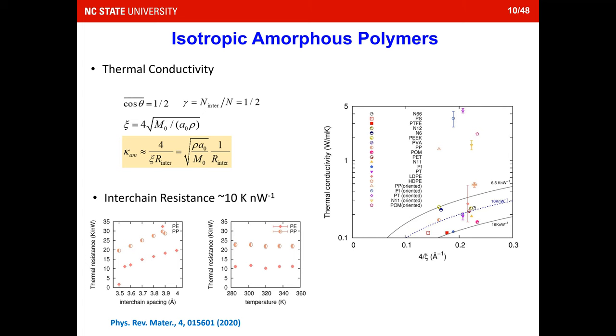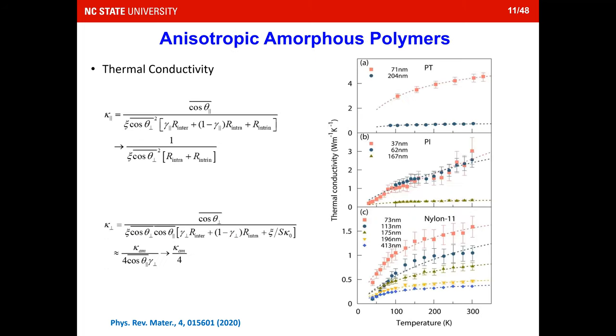Then we switch to anisotropic amorphous polymers. So we derived a few equations that describe the thermal transport in a direction along the chain, or perpendicular to the chain. And we tried to fit experimental data conducted on different polymer fibers with different diameters. So the dashed lines are our fitting results, and the solid dots and squares are the experimental data. And you can find that this model can explain quite well how thermal conductivity behaves at different dimensions of the fibers and different temperatures.